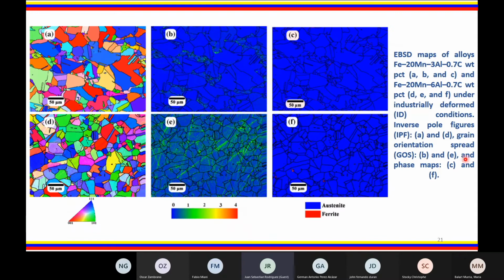When looking at the result of the industrial deformation process, large differences are observed. It is important to mention that the industrial deformation process consisted of heating and deforming. This was repeated 3 times, and finally quenching. In the graph, we first observe that the sample after the deformation and heating cycles does not present texture.